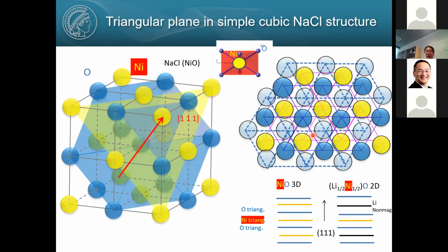So we can have a chance of finding a quantum spin liquid there. And in fact, making a triangular motif in a real material might be easier than you might think. For example, we can make a triangular lattice easily from the famous cubic sodium chloride structure. Okay, so this is the sodium chloride structure. Okay, and this looks quite cubic, without triangles. So why don't you take a look at this sodium chloride structure along the 111 direction, the diagonal direction. Then you can see, along the 111 direction, you have a pileup of triangular lattices made of sodium and chlorine. Well, so this is a picture from the 111 direction.